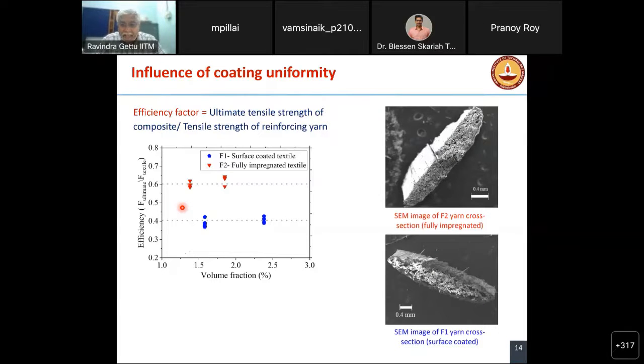So here I have 2 cases where you have a textile yarn. This is a textile yarn. If you see the scale bar, this is about 1 or 2 millimeters. And you can see that here, this is fully impregnated. That means the coating material has fully impregnated the fiber. Here you see that in the bottom, in the F1 yarn, the coating is only on the outside. Inside are loose fibers. So when we are pulling, this becomes more efficient. You see here that we are able to mobilize about 60% of the tensile strength of the fiber within the composite. Whereas here we are only able to mobilize 40%.